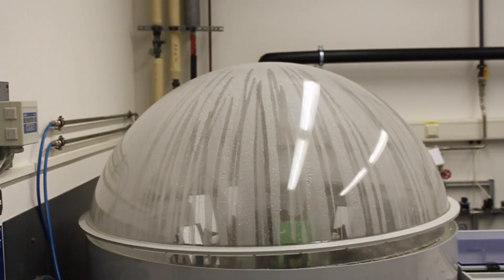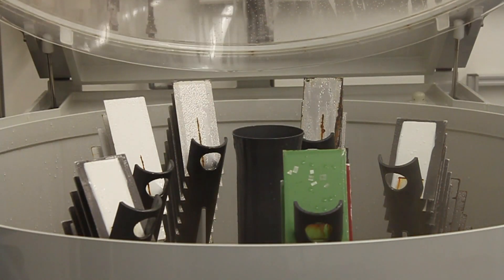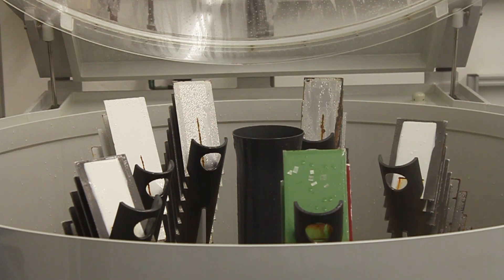The second panel is the result of the neutral salt spray test. This panel was deliberately damaged by a mechanical drill - you see a big scribe at the bottom and some rust spots on the surface where the rust solution has run across the panel. This is just superficial. Even after 480 hours of this harsh environment, we virtually have no under-rusting and no blisters at the scribe. This is a special chamber where you have a sodium chloride atmosphere. Anti-corrosion pigments are one of the more expensive ingredients in the primer, so using Acronal Pro 770, you can replace them with inert fillers or with more dispersion - being more sustainable and saving money at the same time.